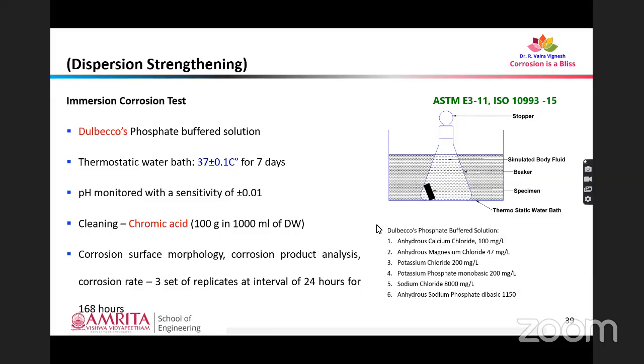Why? Because that has some stabilizing agents for maintaining the pH too. And how it is done is we have made a thermostatic water bath that can maintain a temperature of 37 plus or minus 0.1 degrees Celsius for a period of 7 days, and we have monitored the pH with a pH meter with a sensitivity of 0.01. We have immersed the specimen into a container containing SBF. We place that container in the thermostatic water bath at 37 plus or minus 0.1 degrees Celsius. So that mimics the human body environment.